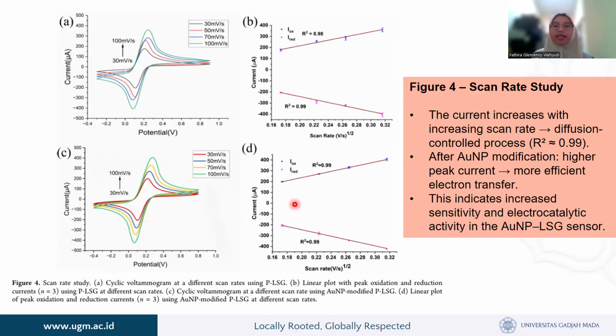And with D, the linear plot after AuNP modification also maintains that R square 0.99, remains diffusion controlled, but with a larger current response, confirming increased electron transfer efficiency. And the meaning of figure 4 is the scan rate affects the current height, indicating a reaction mechanism that depends on analyte diffusion. The addition of AuNP increases the conductivity and accelerates electron transfer. AuNP modified sensors exhibit stronger redox response and higher sensitivity.